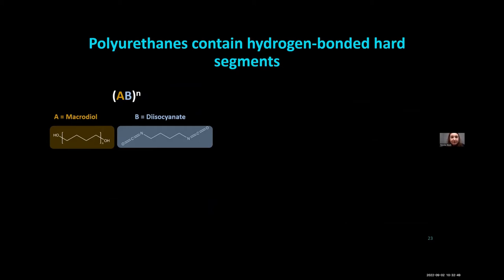We decided to pursue polyurethanes because they are essentially thermoplastic elastomers, or they can be when designed the right way. These elastomers can have similar properties to soft tissue in your body. Especially your eardrum, as I mentioned, is about 10 to 100 megapascals in stiffness, so on the softer end. And so how can we create a material that will mimic this?